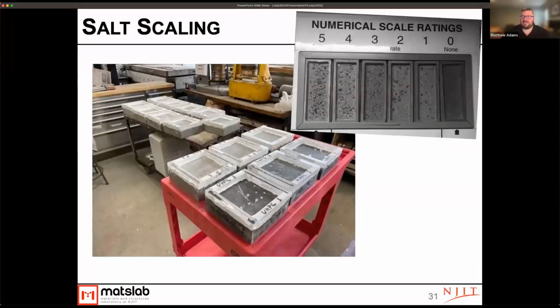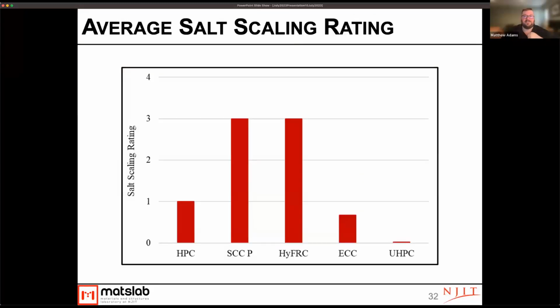Salt scaling is the third of the non-corrosion durability tests we looked at. And for this test method, you take a concrete slab, a small concrete slab, and you put a dam around it, and you pond it with a chloride solution. And then this is more of a qualitative test. You look at the damage to the surface over time to determine its resistance to salt scaling.